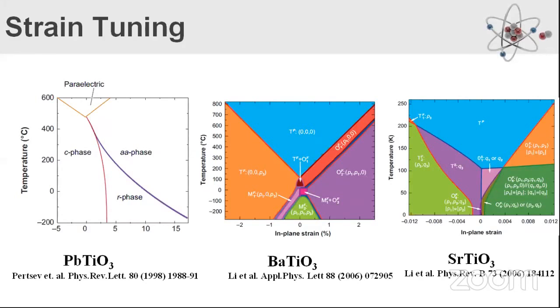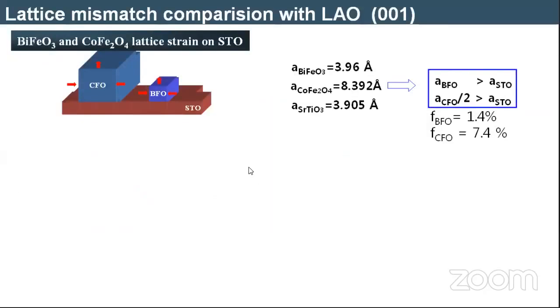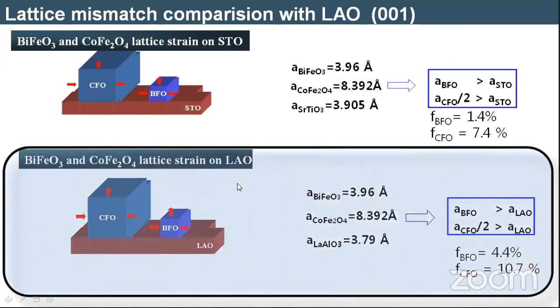These are all theoretically worked out materials. So how is this going to affect my material, bismuth ferrite? I'm going to check it out. I have explained this already in the last part. What will happen if I change the substrate from strontium titanate to lanthanum aluminate? I already mentioned on the first slide that lanthanum aluminate has a lattice parameter of 3.79, which gives a huge compressive stress. Will it grow epitaxially with that much huge lattice strain? You can clearly see around 4.4% for perovskite and around 10% for the spinel phase.